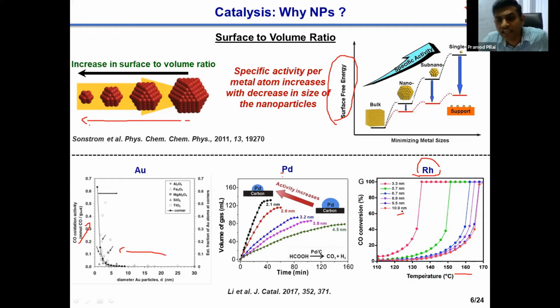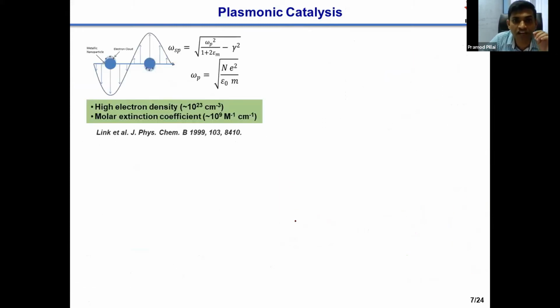So this is a general thing. The size effect is general and uniform for all materials at the nanoscale. But there is something special for plasmonic nanoparticles, that means metallic nanoparticles. The important process in plasmonic nanoparticles is surface plasmon resonance. In very simple words, surface plasmon resonance is nothing but a collective oscillation of the plasma of electrons under the excitation of electromagnetic radiation. This essentially means that the entire electron cloud in the metal can get excited with the help of electromagnetic radiation.